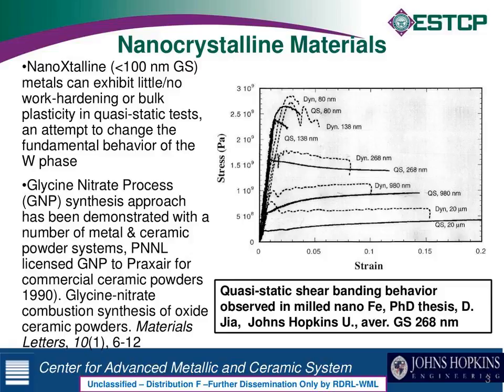So in all these cases, they're all the same material, pure iron, but just through grain size refinement and the Hall-Petch relation, you're getting much stronger materials, but they're becoming plastically unstable. So that's sort of the basic approach we were trying to do with the tungsten heavy alloy, get that same sort of behavior either in pure tungsten or tungsten alloy or a tungsten heavy alloy, which is really a composite of tungsten and the matrix material. So we've been working that approach in some other areas, and I'll mention that a couple of times during the talk.